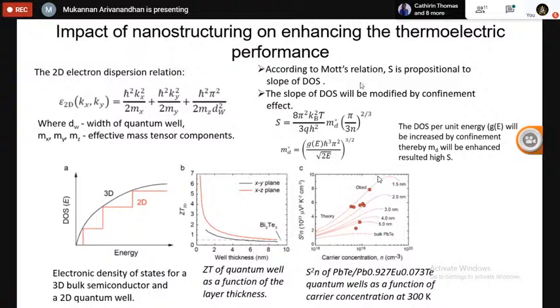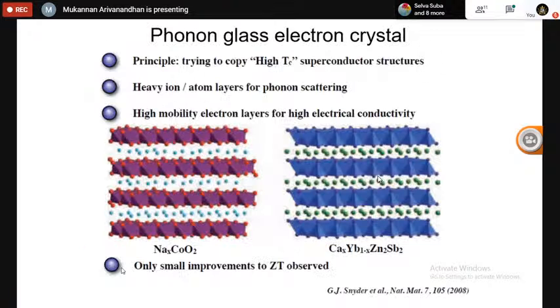And this is some of the theoretically calculated data for ZT for bismuth telluride in two different confinement directions. So in a certain direction, the ZT is quite high, as well as the power factor. The power factor is also quite enhanced by tuning the thickness of the quantum well. If you have very narrow range of quantum well, you can increase the power factor. So like that, these are all the beneficial aspects of nanostructuring the material for improving the thermoelectric performance.